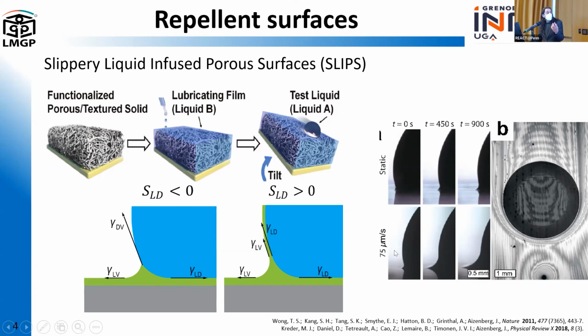But if the water droplet is sliding, even slowly, you can see a strong increase in the size of the ridge, and due to that, there is a strong lubricant depletion. You can see that on this picture, where the droplet is moving downward, and you can see the trace of lubricant depletion behind the droplet.